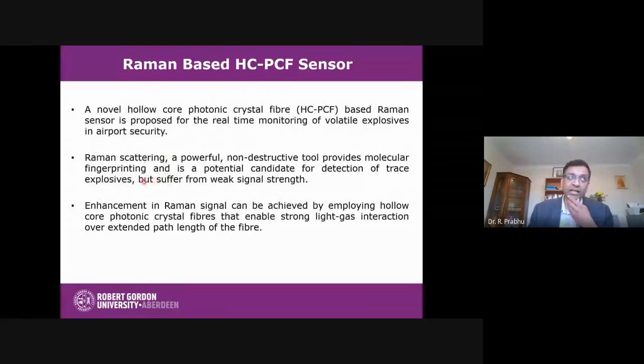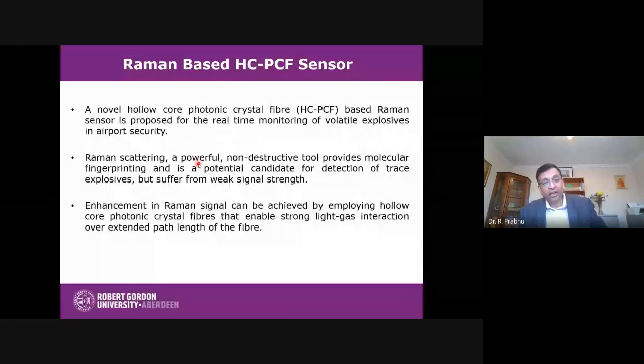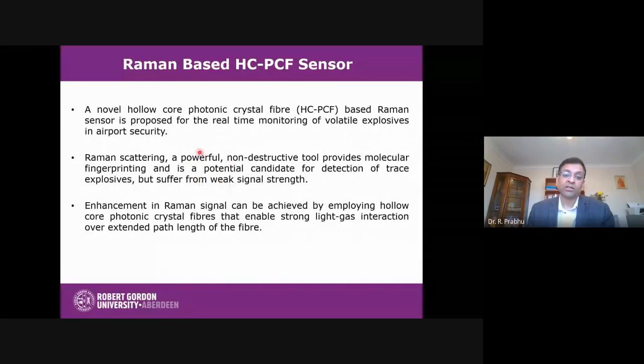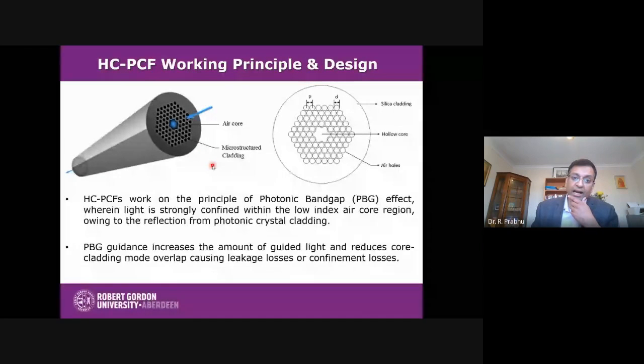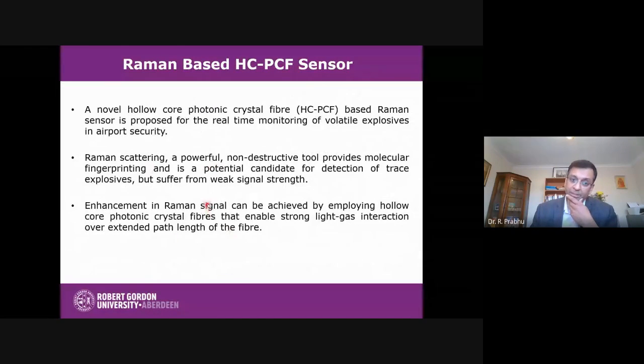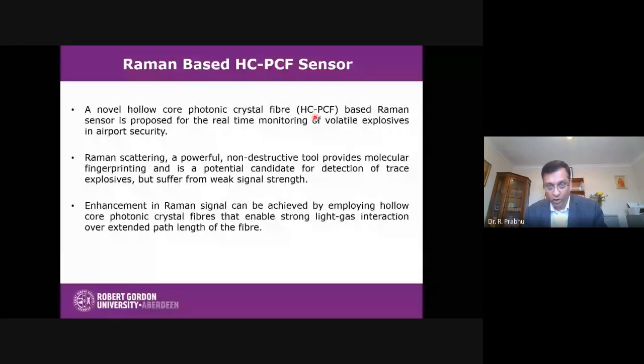But the problem with Raman scattering is that it is very, very less sensitive, or it requires very strong laser power to detect the signal. Especially if it's a trace vapor, it's very, very difficult to detect these gas vapors. So we were trying to integrate Raman spectroscopy along with PCF, hollow core PCF, to enhance the sensitivity. Currently, this project is ongoing.